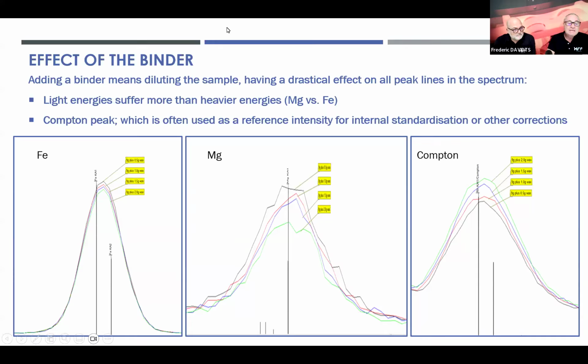So what we can see if we are now going to dilute, yes, it's dilution. If we add binder to our sample, it does have a serious effect on the intensity of the elements that we want to analyze. For example, for iron, the upper one, and it's maybe difficult to see, we had a 9-gram sample and 0.5 gram wax.